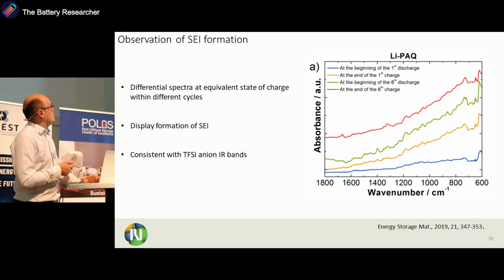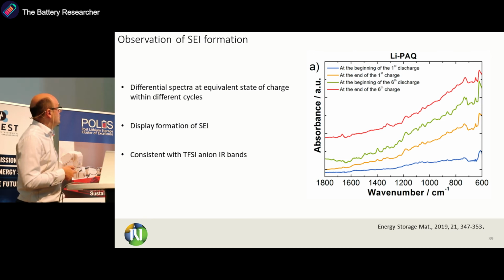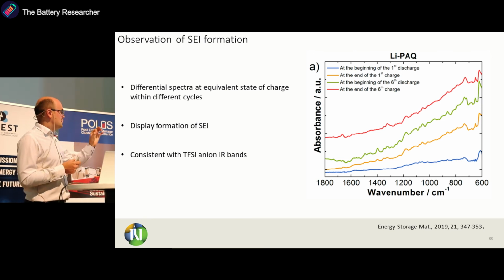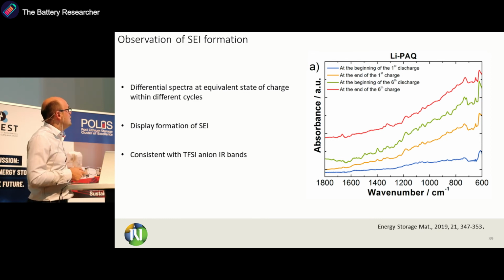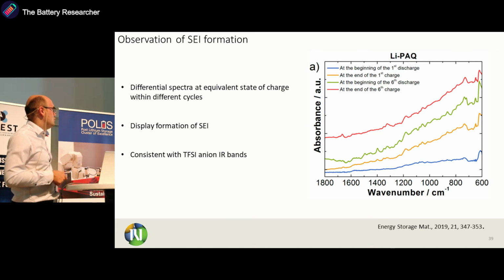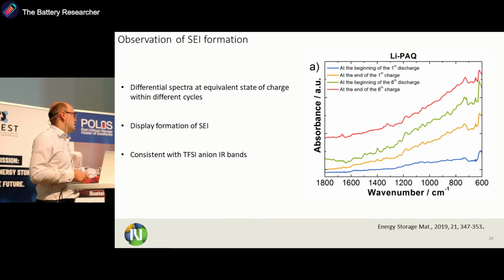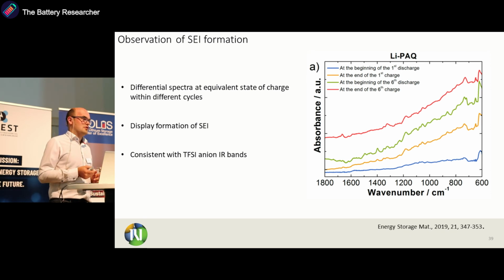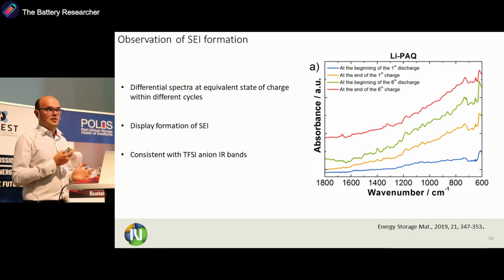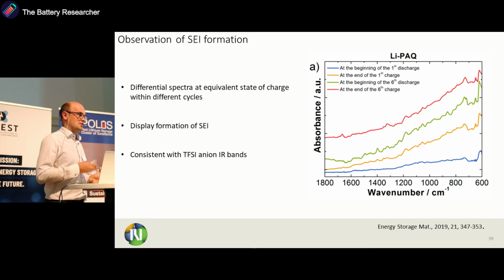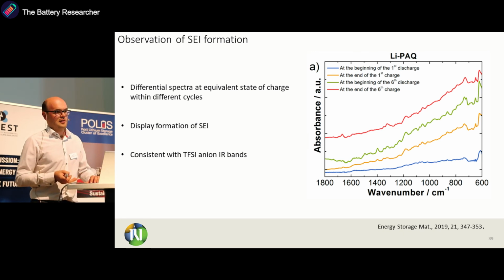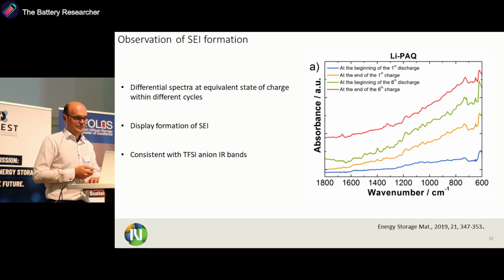We could also do some observation of SEI formation on the cathode if we take the spectra at same state of charge but in different cycles. And if we analyze and take a look at the literature, we see that basically these infrared bands, they belong to TFSI anion. So basically also we have probably some TFSI decomposition, although we don't see it because Coulombic efficiency in these systems is quite high. So it's above 99%, and you would not expect it, but it's there.